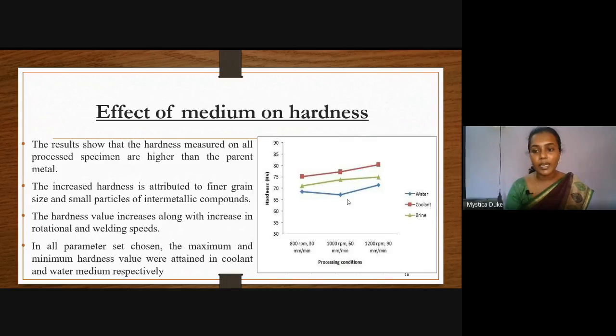Here you can see again the coolant produced higher hardness for all the parameter combinations. This is again attributed to the finer grain structure that is developed in the material. Because with finer grain structure, the hardness obtained increases, as we know already. And with the parameter combination, the hardness also kept on increasing.